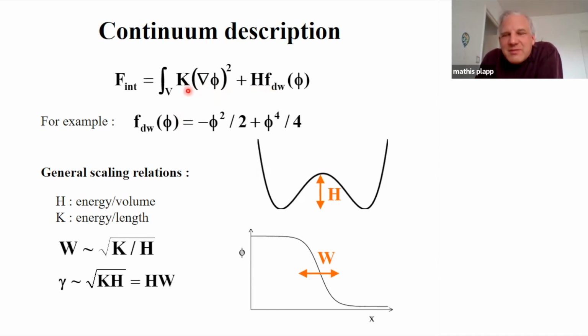But you can also use them in a different way, because we can start from very simple dimensional analysis and see that F here is a free energy, so it's in joules. This is a volume integral. If F here is a dimensionless function, then my coefficient H is dimension of energy per unit volume. Okay. In the other term here, there is a gradient squared, which brings a length squared in. So the dimension of K is energy per unit length. That means that if you take the ratio of these two coefficients, you get a length. If you take the square root, a length that I will call W. And if you take the square root of the product of the two, you get energy per unit area.